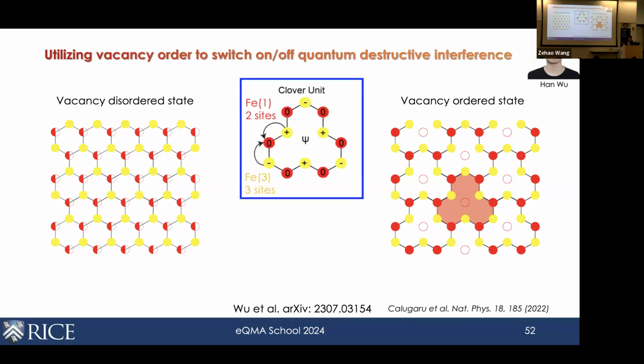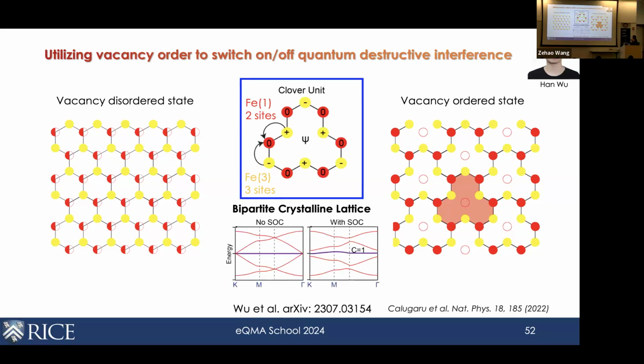And this unit, my student Han Wu here, he called the clover lattice. And it turns out the yellow and the red sites are actually different iron sites. This is an example of a bipartite crystal lattice, which means that nearest neighbor hopping is always between two different sublattices. And theoretically, it's also been known that if you have a bipartite lattice where the number of sites belonging to the different sublattices are different, in this case there are 2 versus 3, then you're guaranteed to have zero modes, which are these topological flat bands.